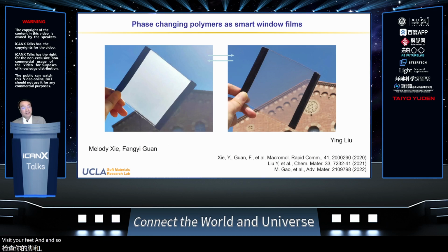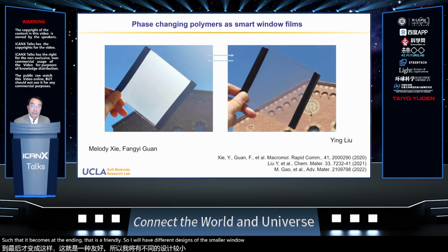And very recently we also showed that by reformulating the BCPs, at room temperature this film is clear. But when the temperature reaches 35 degrees Celsius, there is a phase separation occurring in the film such that it becomes opaque at the elevated temperature. So we have different designs of smart window films based on the BCP film.